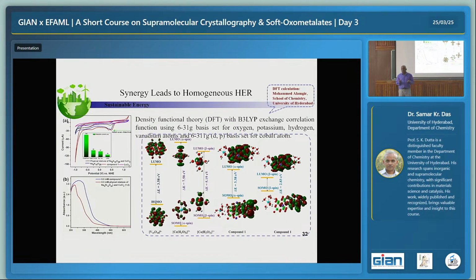Now, how it happens, I would like to tell you. The electrochemistry machine will give some electrons. By what will the electron be taken? Will the cluster take it first or the cobalt, that we want to know. Now we see that the LUMO is delocalized here, and the SOMO, single occupied molecular orbital. We found that in the case of the cluster, the LUMO is localized on the vanadium cluster. That means when the machine gives electrons, the vanadium will be reduced first. And we believe the electron then goes to cobalt. Cobalt 2 becomes cobalt 1, and then cobalt 1 reduces water to hydrogen. This is from the theory.